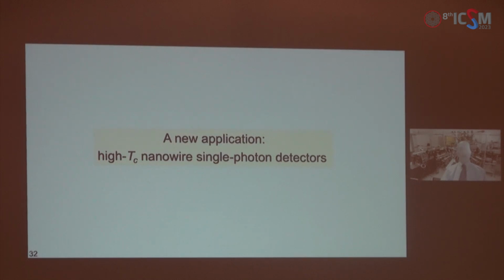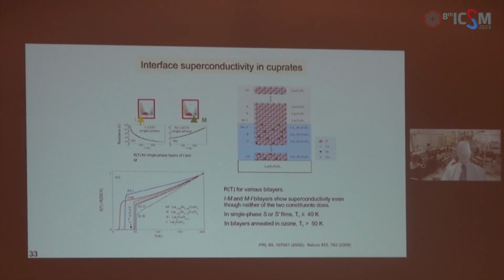I would like to end on a high note, and for any practical work, it should be the prospect of some real-world electronic applications. Some years back, our claim to fame was the discovery of interface superconductivity. We used two materials, underdoped lanthanum cuprate and heavily overdoped lanthanum strontium cuprate. Neither of these is superconducting per se in isolation, as a single phase. But when we bring them together into intimate contact, then high temperature superconductivity magically appears, and it can be as high or even higher than in any single phase lanthanum strontium cuprate.